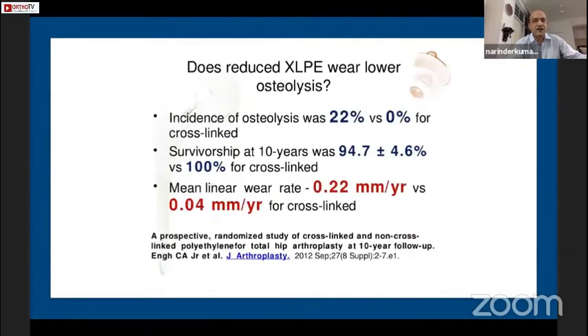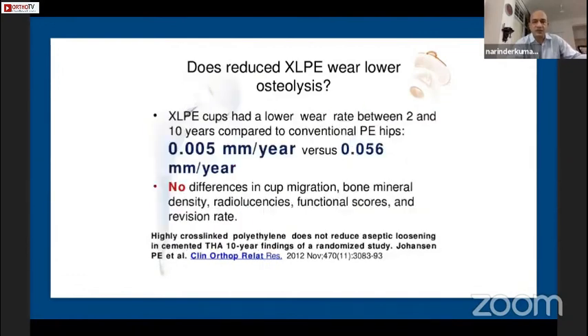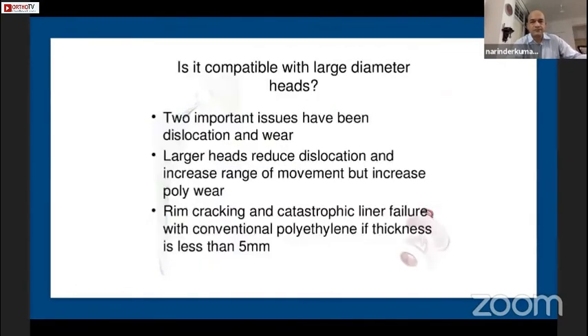But does this wear lead to decreased osteolysis also? Yes, it does. We have 10-year follow-ups, we have 15 years and 20. Now 20-year follow-ups also close to being available, which shows that osteolysis is almost nil at 10 years in this study, but longer term studies have shown that the osteolysis is much, much lesser.